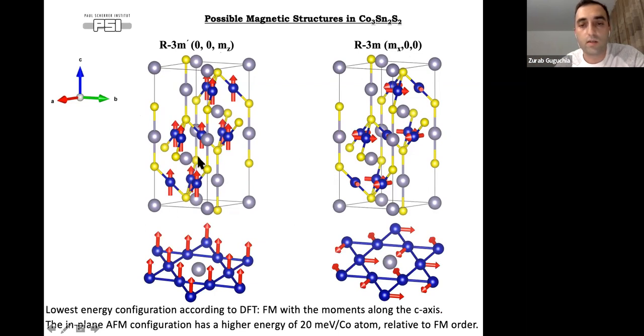So according to DFT, the lowest energy configuration is the ferromagnetic one. And this one has an energy about 20 millielectron volts per cobalt higher than it. But this means that the energies are not very different, so these two energies are relatively close. And then the idea was, okay, when we increase the temperature, maybe thermodynamics somehow changes this balance between these two structures, and somehow it favors the in-plane antiferromagnetic state. But to check this